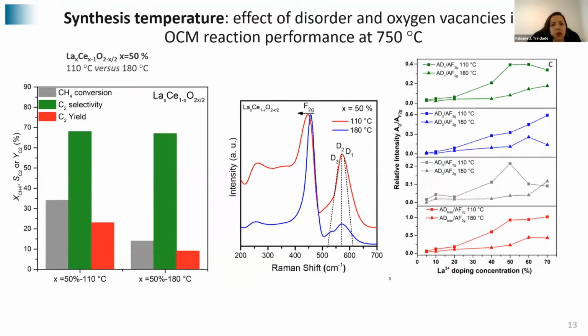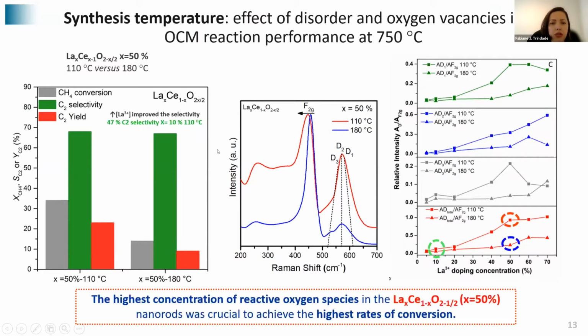Another variation that we wanted to test was to study the effect of the synthesis parameters. Here we have the samples synthesized at 110 degrees and 180 degrees. Basically we expected them to be the same, but remember, we have a different amount of oxygen vacancies. This gives the better performance of the samples synthesized at 110 degrees, which have higher amounts of oxygen vacancies. But an interesting point here is that the amount of oxygen vacancies influenced conversion, but the lanthanum was really important for selectivity.